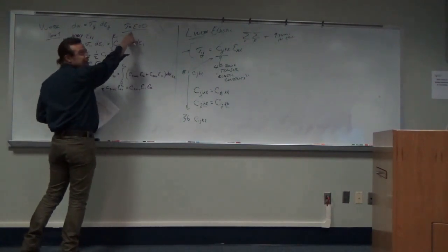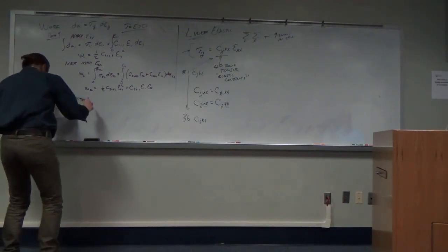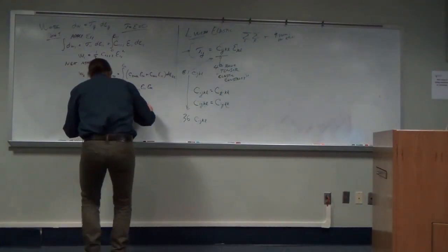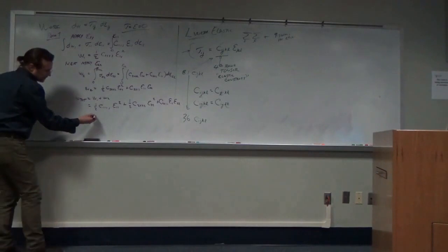So in the second integral, notice we had 2 terms. That's because epsilon 11 is not 0 anymore. Whereas before, we started out in a stress-free, strain-free state, but now in the second step, we don't have that. So now we have the total work of W1 plus W2 equal to 1/2 C1111 epsilon 11 squared plus 1/2 C2222 epsilon 22 squared plus C2211 epsilon 11 epsilon 22. So the total work is going to have a uniaxial term, and then this cross interaction term. Okay?